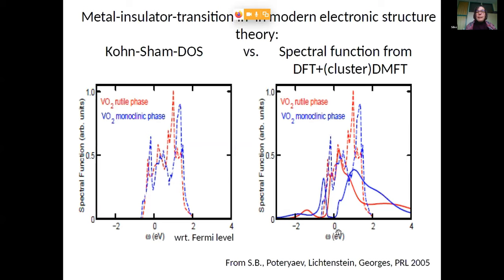So what you see is that in the metallic phase, you have a slight narrowing of the bands, and you start to form a satellite feature here at lower energies. And that's it essentially for the occupied part of the spectrum. So again, the Fermi level is at zero.